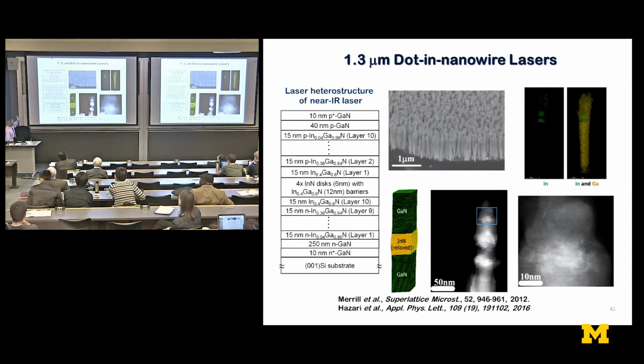So the last thing, now I'll switch to really the present, 2016 and 2017. We have been growing nanowires just like Zetian. Our nanowires with the nitride system are self-organized nanowires, arrays of nanowires. And we grew this graded-index separate confinement heterostructure laser structure. And here's the active region, and what is new here is we went all the way to indium nitride. And nobody had ventured to put indium nitride in these nanowires.